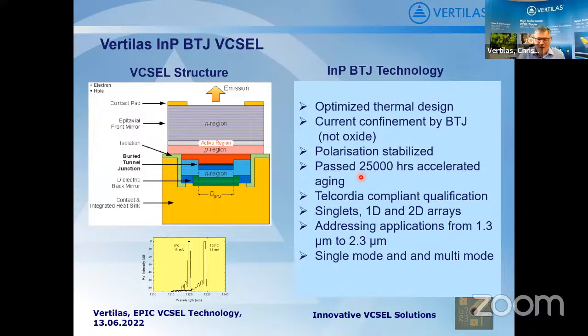Okay. And as was mentioned in the previous presentation, if you go from gallium arsenide to indium phosphide and you want to get a high reflectivity mirror, especially for the back mirror, you need many mirror pairs. So we have solved this by replacing the epitaxial DBR with a dielectric DBR, which gives a number of benefits in our design. And at the bottom, we have basically a galvanic pseudo substrate, which acts as a very nice heat sink. So in summary, we have an optimized thermal design. The current confinement is done by a buried tunnel junction. Our lasers are polarization stabilized, which is critical for many markets and applications.